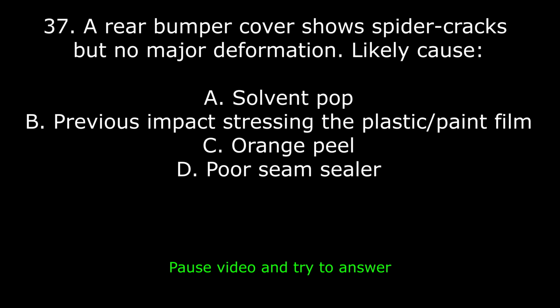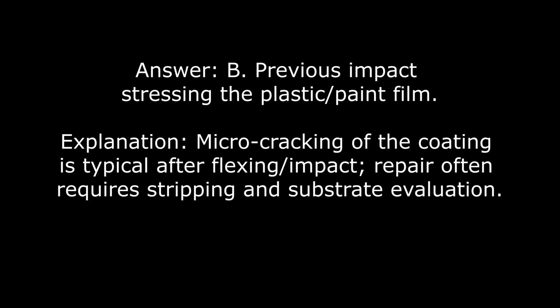37. A rear bumper cover shows spider cracks but no major deformation. Likely cause: A. Solvent pop. B. Previous impact stressing the plastic/paint film. C. Orange peel. D. Poor seam sealer. Answer: B. Previous impact stressing the plastic/paint film. Explanation: microcracking of the coating is typical after flexing or impact. Repair often requires stripping and substrate evaluation.